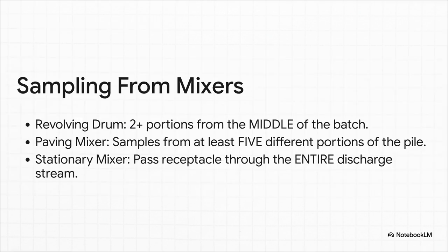Okay, take a mental snapshot of this slide right now because these are guaranteed exam questions. For a ready mix truck, you're sampling from the middle third of a load. For a paving mixer, it's at least 5 different spots.